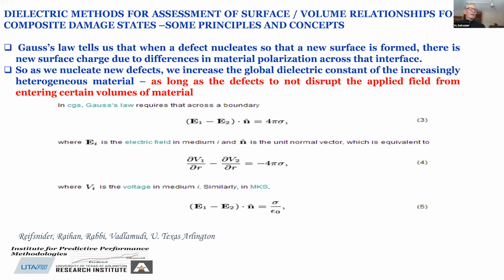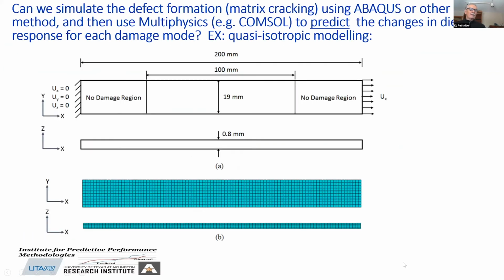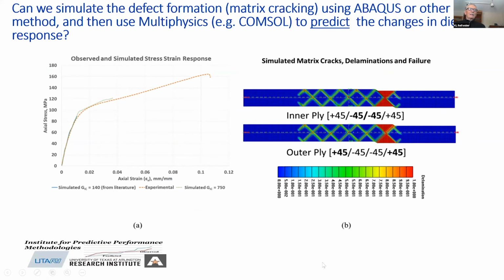Well, supposing I disrupt the voltage flow through the material, then I will exclude certain volumes of material from giving me a dielectric response. So I can't see this dielectric polarization if this material has been disrupted in some way to keep the signal from getting there. And that's exactly what happens. Now we're going to look at a model through the thickness, a quasi-isotropic specimen, modeled in Abaqus, then going into COMSOL to predict the actual numerical values of the dielectric change. And if we start to do that, we get a very interesting response. And just a few years ago, we were completely unable to get these results. So it's thrilling for those of us who've been in this field a while.